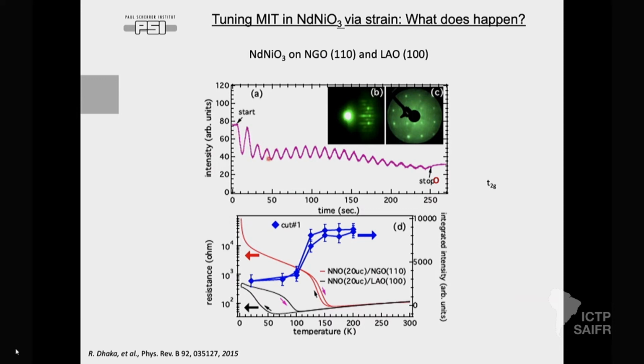Here you can see the RHEED oscillation, which tells you how many layers you deposit. In the end, you stop and can say you have this thickness. It was 20 unit cells. Here is the RHEED showing ordering of the surface, and here is the LEED, which also shows the surface post-growth, already moved to the ARPES station. So the surface is well ordered, showing orthorhombicity signs, which are those streaks between the main peaks.